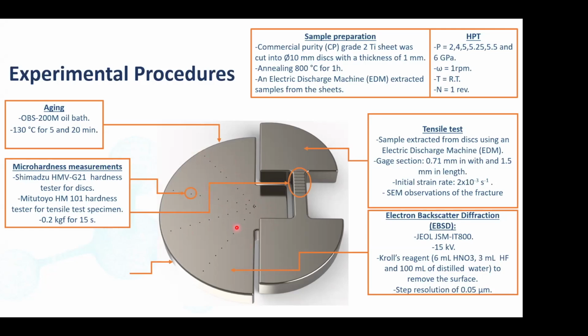microstructure is evolving. And microstructural evolution I will talk about a little bit later, but as I said, once we get a steady state grain size, a saturation grain size, when dislocation generation is balanced by dynamic recrystallization, we will not get further refinement with HPT processing. So this gives a chance to material that's closer to the center to evolve into the fine grain size that we get first in the periphery. So depending on the number of turns, depending on the distance from the center, we can control, as much as we can, the homogeneity of the ultrafine grain distribution in this way. So measuring the hardness is important for this aspect.